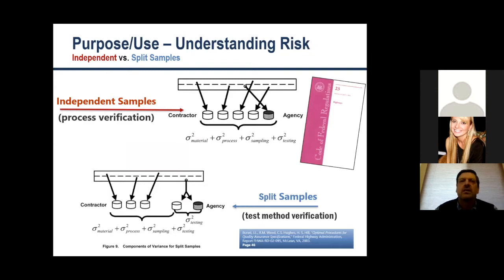Now, the Code of Federal Regulations, 23 CFR 637B, states that if on a project the contractor is performing quality control and the agency or their representative is performing acceptance tests, the samples that are used by the contractor and the agency or the DOT have to be independent. And this slide is an effort to illustrate that. So this would be a pavement. So up in the top here, we've got a pavement, and 5 cores have been taken out. So 5 random locations were identified, 5 cores were taken.